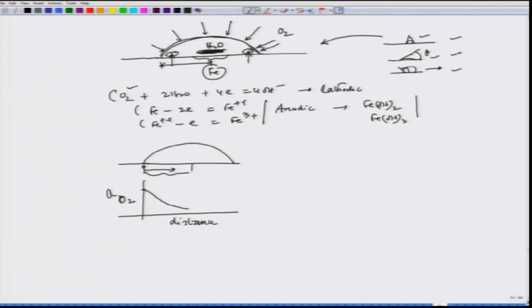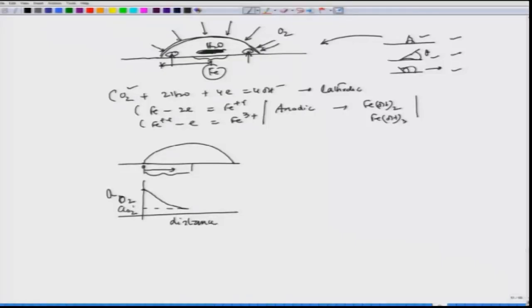So, this particular line may have its own plot depending on the diffusivity or the temperature of the atmosphere. Even though this water droplet remains momentarily, still this situation can arise. So, that means we see the concentration activity of oxygen here, this is 2, let us say, and this is activity of oxygen, this is position 1, we have a difference in concentration. Once we have a difference in concentration, if I try to see the E ox red at position 1 and the E ox red at position 2, this becomes higher than this.